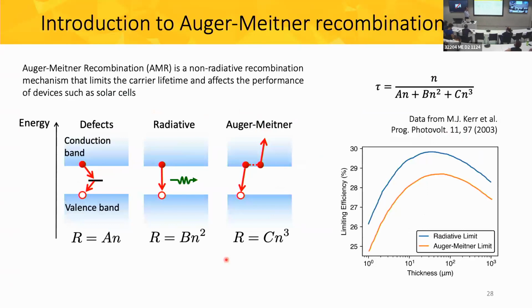So what happens in the recombination? In the material you have both electrons and holes that recombine with each other, and the energy can be dissipated in the form of photons or heat. So in the radiative process, the electron recombines with the hole and the excess energy becomes a photon. But also the energy can be lost to heat through defects in the middle of the band gap, which is known as the Shockley-Read-Hall recombination process.